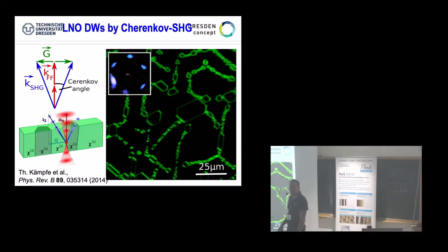So what you do physically in your experiment is you position your detector at these positions, left and right, or, like in a dark field experiment, you just block the center beam. You just take the apex beams, and if you put them on the back focal plane, you see exactly the symmetry of your system. So you can also check locally what the symmetry of your system is somewhere inside. So this is really nice.